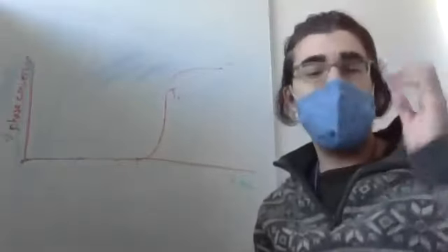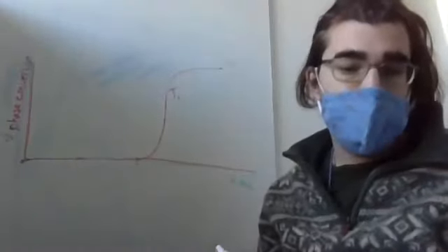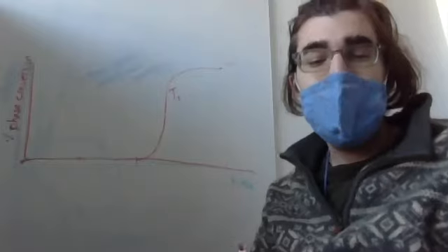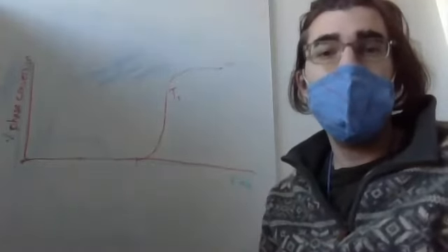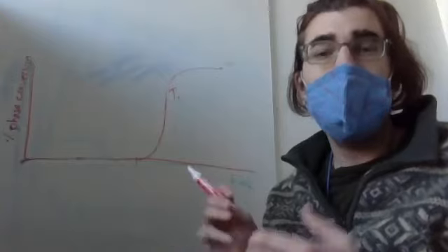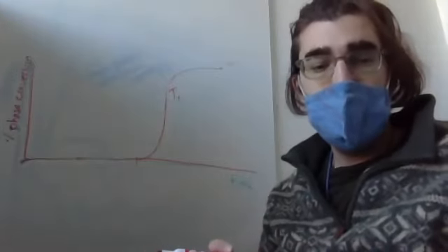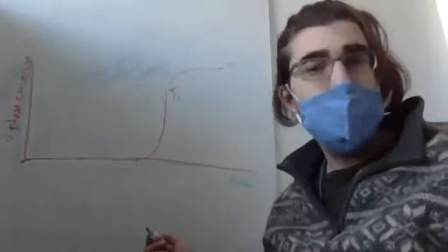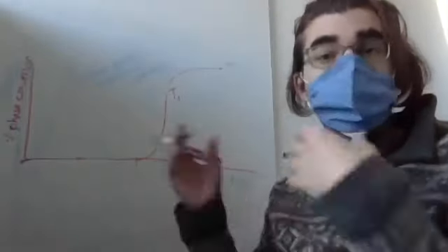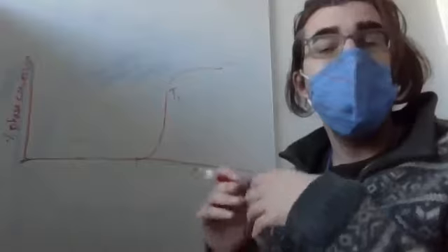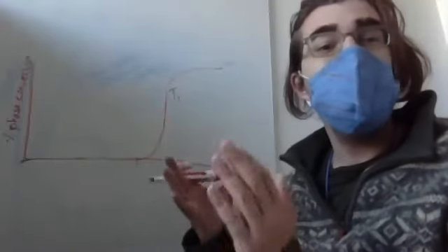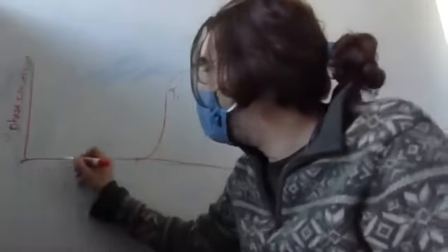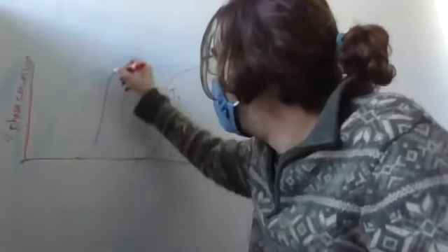So now we can repeat this experiment again at different temperatures and track how long it takes for a new crystal to form, or for this recrystallization to occur. And if we go to a higher temperature, what do we think is going to happen? Atoms will be able to move faster, right? The interfacial energies will be less, and it will take less time for a new phase to nucleate and crystallization to occur. So if we go to a higher temperature, it might look like this.